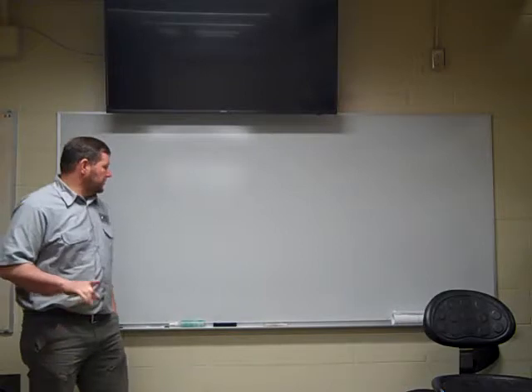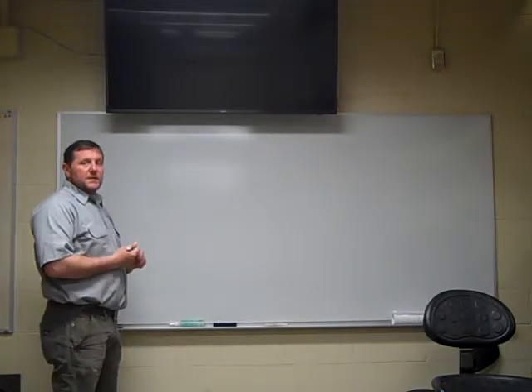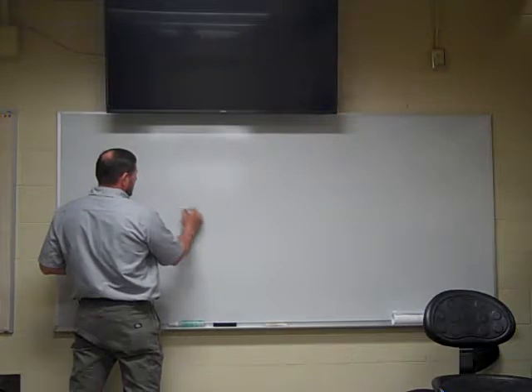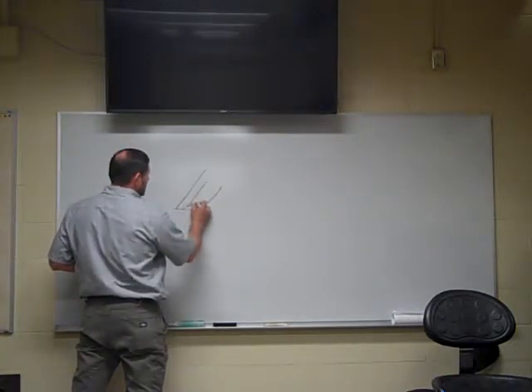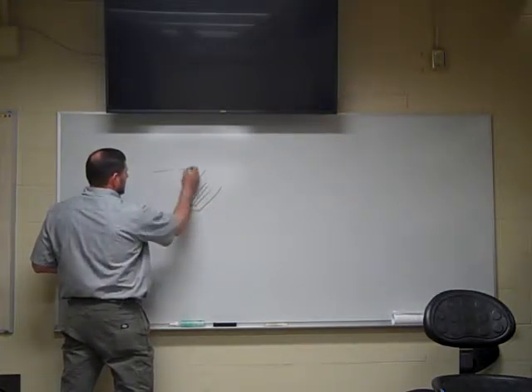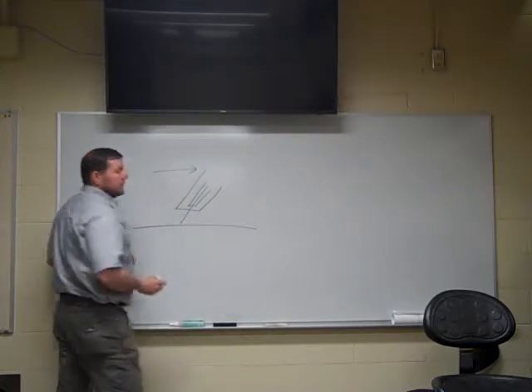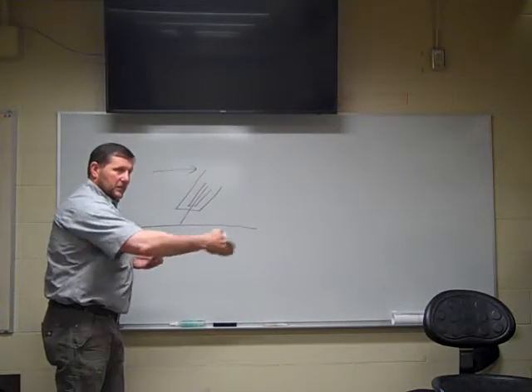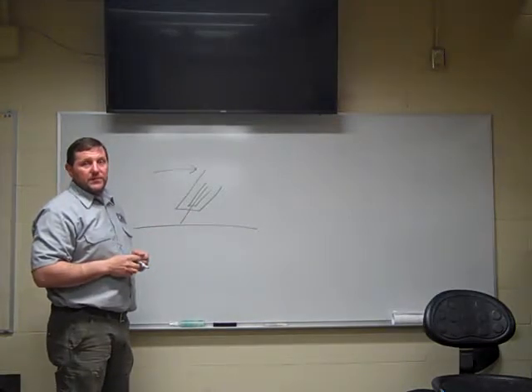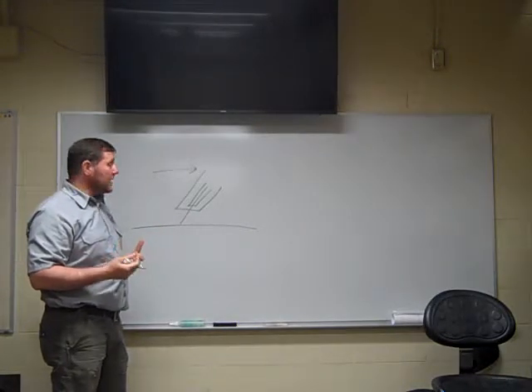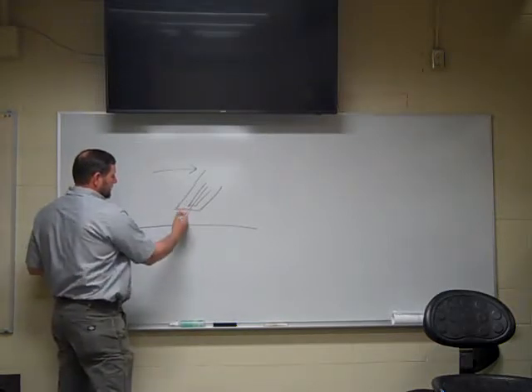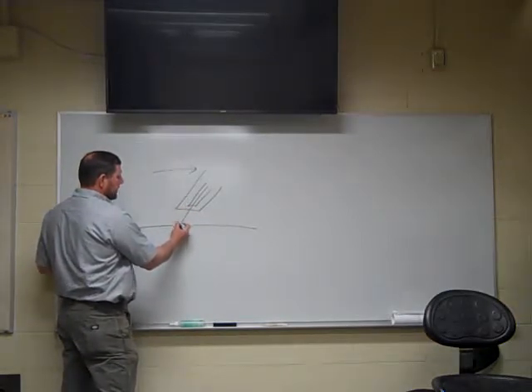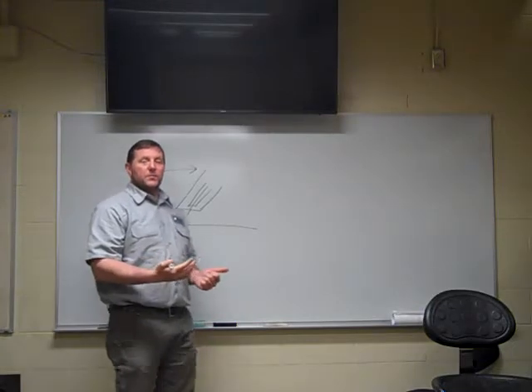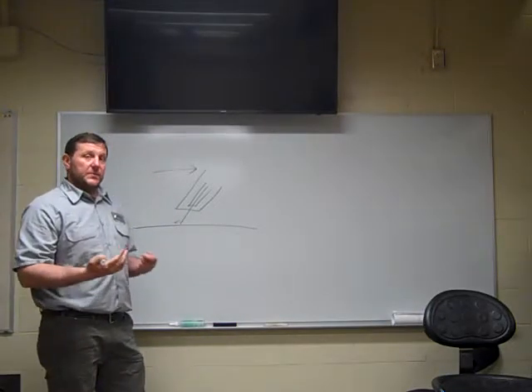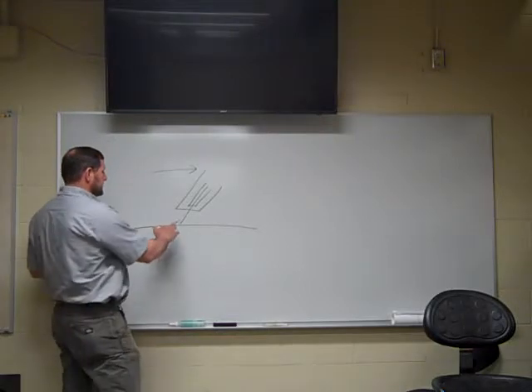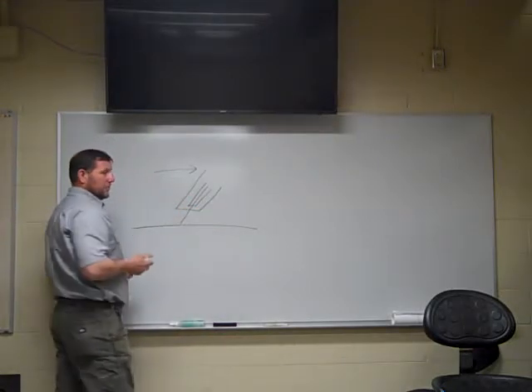The number one thing about flux core, like we said, it's like stick welding. So as you're welding, you're going to be welding in a backhand progression. So here's my nozzle, wire coming out. I'm going to be welding in that direction. So flux core is a backhand weld. There's a few times where you can weld it forehand. But as you're welding forehand, for example, if I'm going in this direction, a lot of times that flux wants to fall out in front of the weld pool, get trapped in the weld pool, and gives you slag inclusions. So typically when you get into industry, when you're welding with flux, everything's going to be welded in a backhand progression.